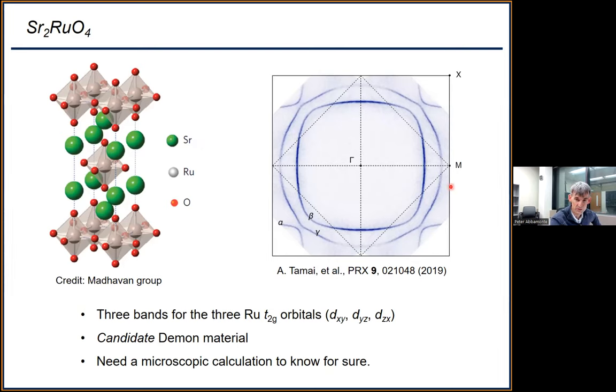If you do photoemission, it has three different bands. They derive from the three d levels of the ruthenium, and the consequence is there are three different Fermi surfaces. So this material has three different flavors of electrons. It's not just two, it's actually three. And so you could say it's a candidate demon material. It's not proven that it should have a demon, but it's certainly possible that it could.